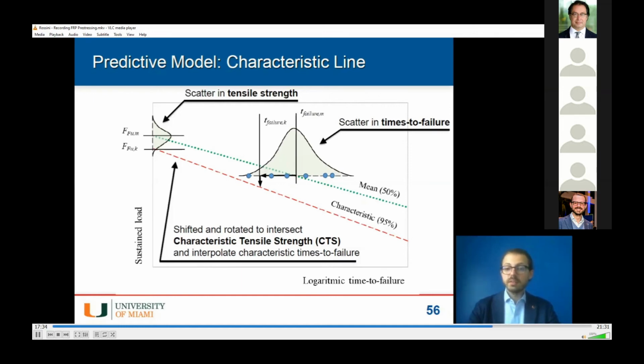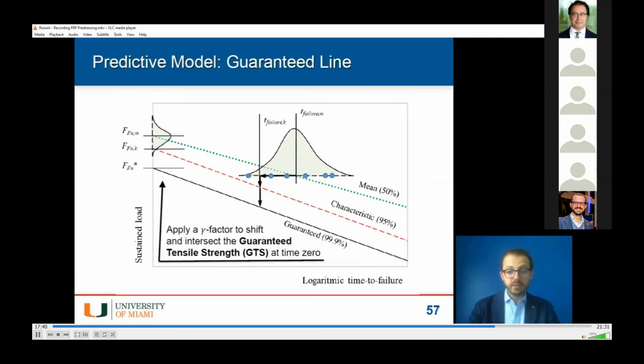But 95% is not enough. You don't want 5% of your structure to fail when you design. You want much less. In order to do that, you need to apply a gamma factor, a safety factor, that shifts your characteristic line down to a guaranteed line that is defined in a consistent way between ACI and Eurocodes and takes care of 99.9% of your failure points.